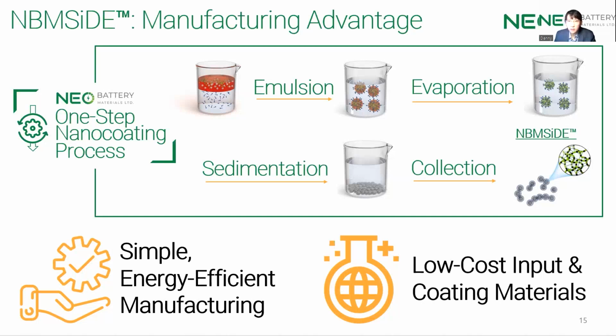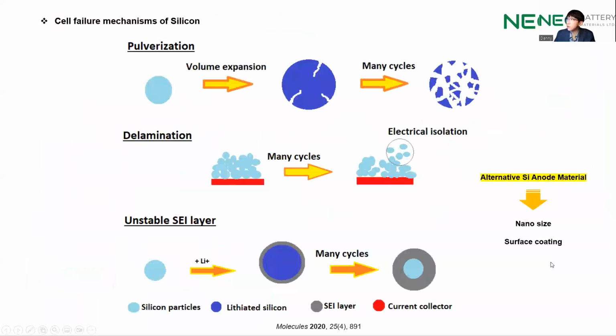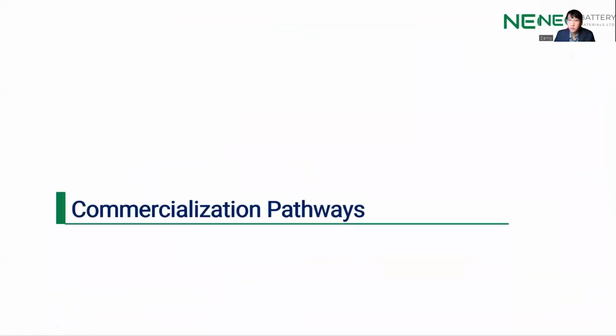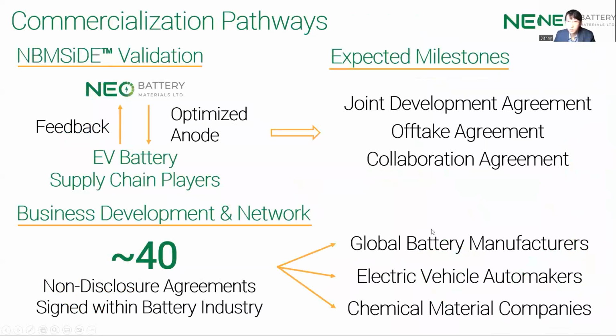EV battery manufacturers and these OEMs don't require the commercial level life silicon anode performance of 1,000, 2,000, 3,000 cycles. But these manufacturers are looking for potential in the performance and economics of our silicon anodes, which is around 300 cycles. And when the specifications and performances match the requirements of these manufacturers, you can expect, as we have seen here, the expected milestone activities of joint development agreements, offtake agreements, and or collaboration agreements.